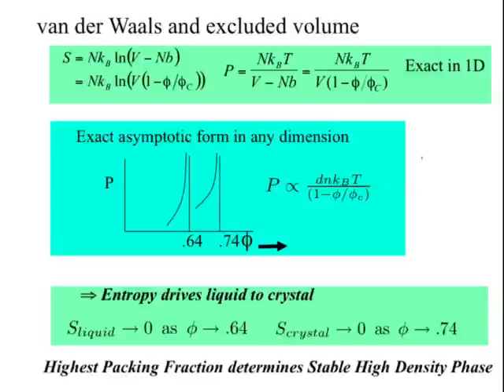Everything's touching, everything's jammed. Now what you do is you take each of those spheres and you put it in a little cell, okay, in an FCC lattice that fills the room. You've got 64% filling. You could have 74% filling. That means that inside each of these little cells, you have lots of room to move around. So the entropy of the ordered phase is higher, right?